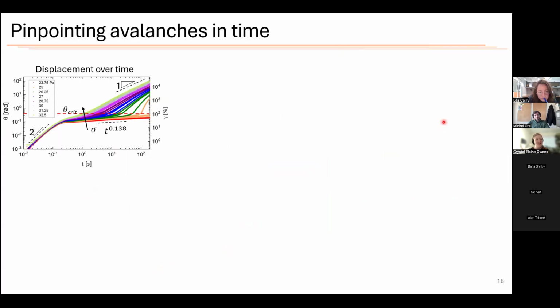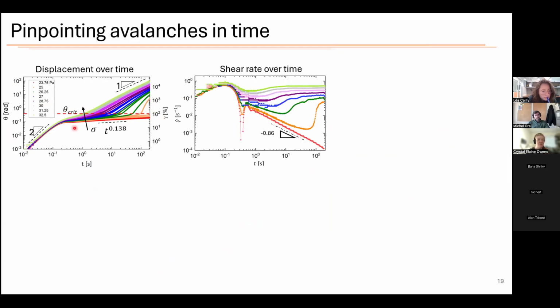Now we can look into this in a little bit more detail. Here we want to pinpoint what is happening when, because right now we can just see the curves and everything is kind of like rising. At some point we have this critical strain, critical displacement, which is useful. Now we plot this on a different scale, which is looking at what is the shear rate over time. So again, this is applying a constant stress. And so we can see at the lowest cases, we see the material is slowing down. That's because this is on a log scale.